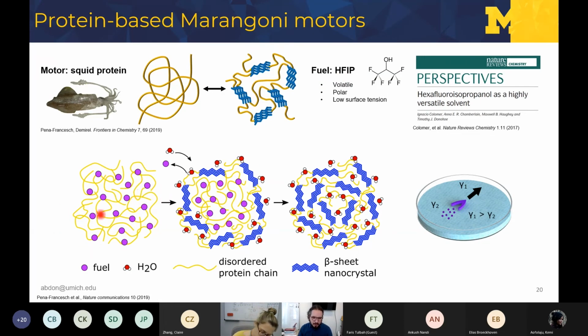So when we have this material, you can see here in this schematic, you have some amorphous material embedded with this fuel, and as soon as it comes in contact with water, this fuel is released, and as it's released, you start seeing the reformation of these beta sheet structures, right? So it's a kind of exchange between fuel content and crystallinity in your material. So this is great to help regulate this release of the fuel, and the whole point of this is you can fabricate some microstructures from this motor material, this protein. You can make structures that have some anisotropy. You can generate this anisotropic surface tension gradient that will give you some Marangoni propulsion.